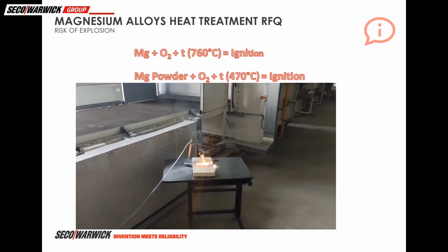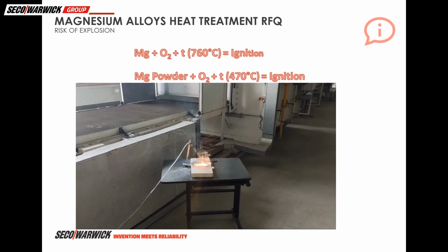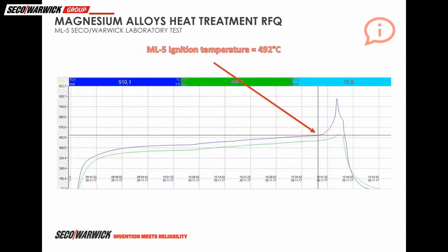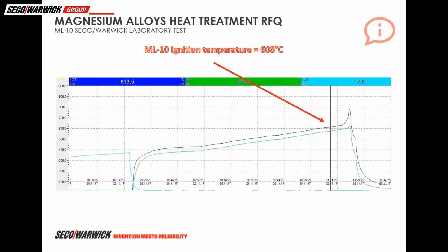The challenge of this project was to get rid of the oxygen from the furnace atmosphere in a safe and ecological manner. Our lab tests have shown that the lowest ignition temperature of the ML5 magnesium sample is 492 degrees centigrade. While lab tests with a sample of the ML10 alloy showed that the lowest ignition temperature for this alloy was 608 degrees centigrade. So it is much lower than the figure of 760 degrees C given in the sources.